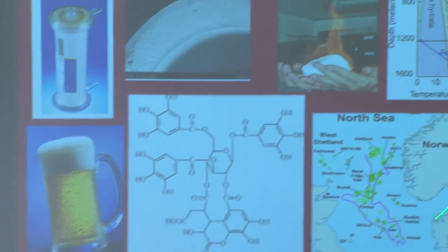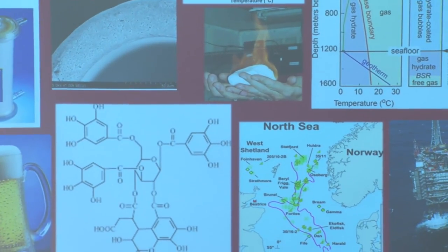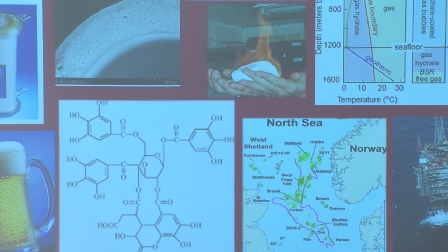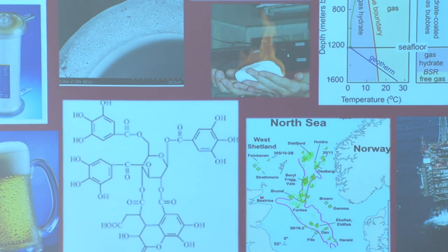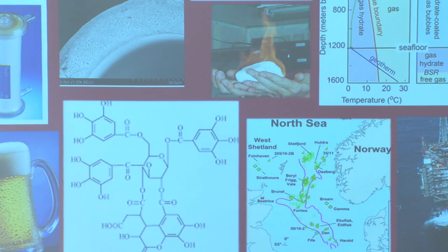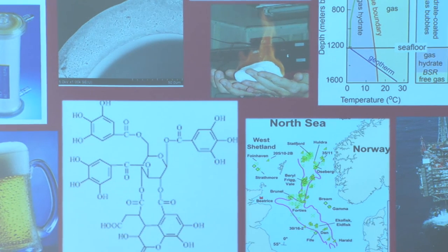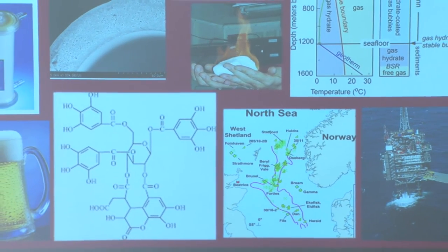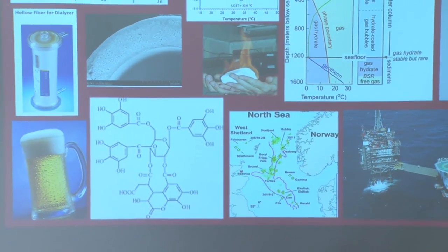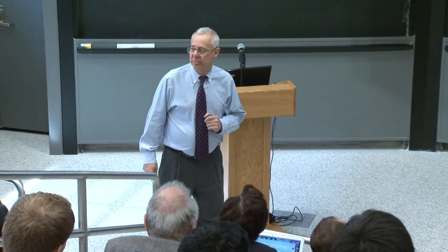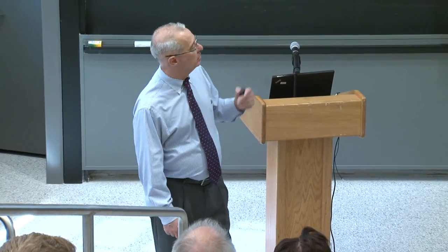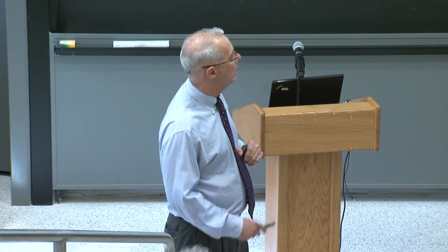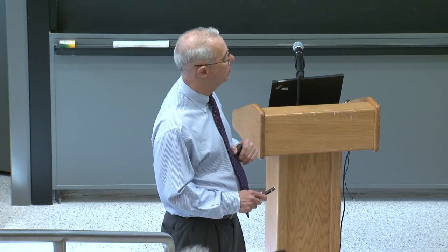So the technology that has been used up until recently was 20% methanol as an antifreeze to prevent crystallization or solidification of these hydrates. We developed a polymer based on lowering its lower critical solution temperature properly that works at 0.5 weight percent relative to the natural gas content of the pipe. So as you can imagine, it's much more environmentally friendly than the methanol, and it's used in these North Sea fields.